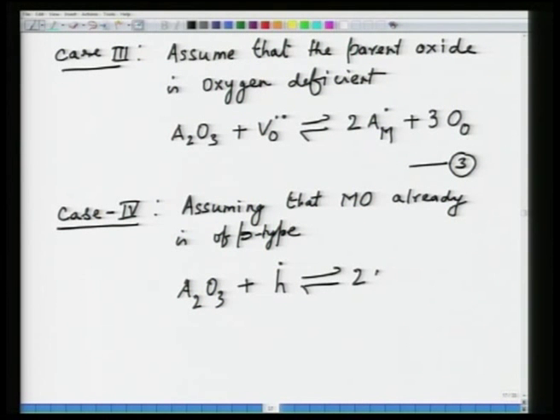So, both the A's go to M site, 2 positive charges. Now, in this case, since you had already holes present, and let us say 2 O_O and half O2, one of the extra oxygen goes out, since you have to maintain the site balance. So, here I do not create any defect on this side, all I do is make it 2h⁺ just to balance it electronically, and now you also have site balance. This is another kind of reaction that would be possible if the material was of p type to begin with.